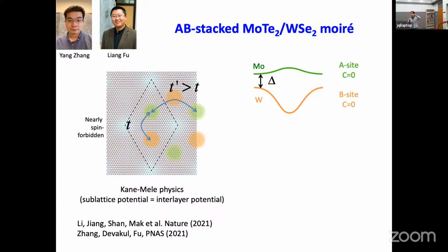You can imagine that if I use a perpendicular electric field, I create a Stark effect, and that can shift the relative band alignment between the molybdenum band and the tungsten band. And it was shown by Liang Fu and collaborators that these two bands actually correspond to, I have some difficulty controlling this mouse.